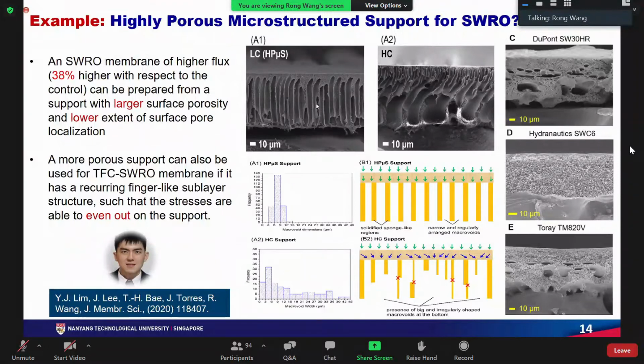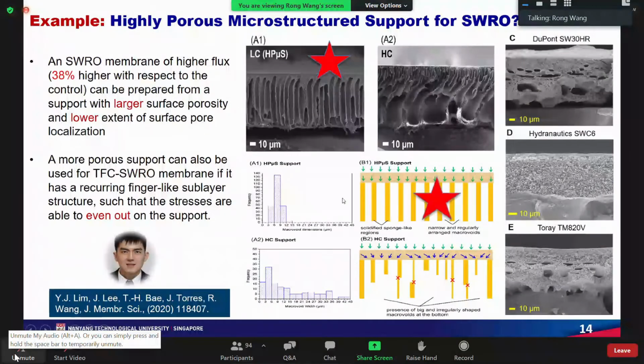You look at the structure like this. Yeah, this is the structure we developed, and we did the analysis, and also we measured the mechanical strength, which is strong enough. But because of this more porous structure, it reduces the mass transfer resistance significantly. We can enhance the water flux for this membrane. And this work was done by my PhD student, Lin Yujie.